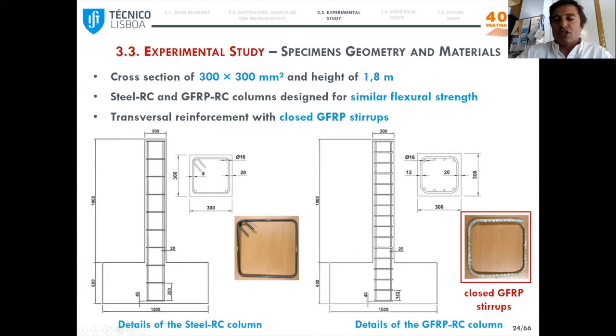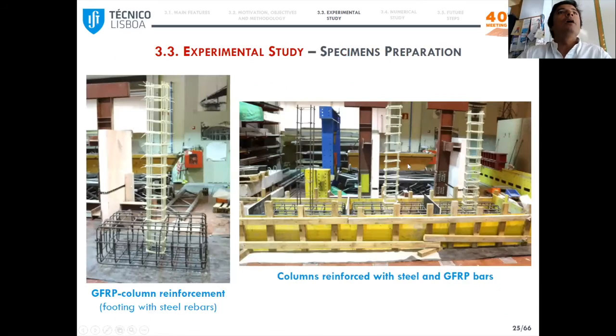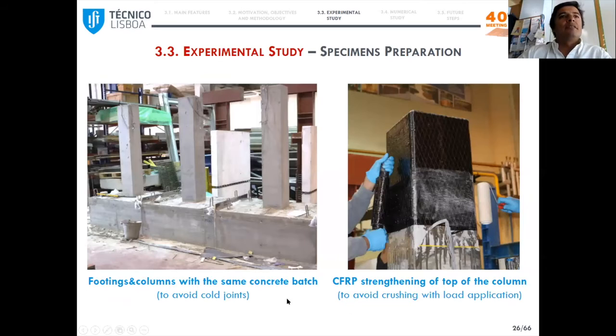Here you can see the geometry of the specimens. As I mentioned, they had full scale, square section with 300 millimeters, 1.8 meters of height. So the steel and GFRP longitudinal rebars were designed to provide similar flexural strength. And here you can see a detail of the closed GFRP stirrups used in the columns. Here you can see some details of the specimen's preparation. So you can see that the footings, they had only steel rebars. And here you can see the columns after demolding.